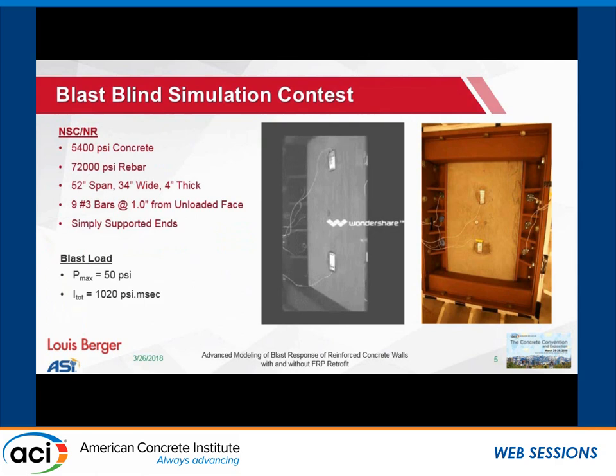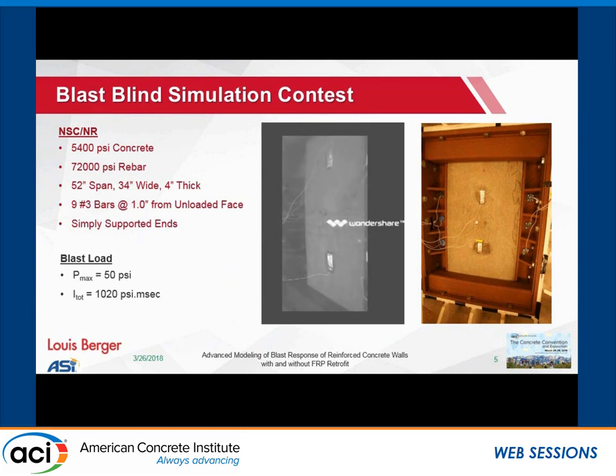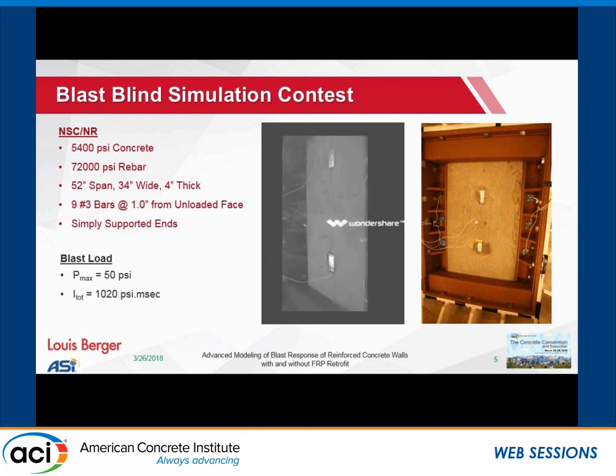This is the typical normal strength concrete case. The testing video shows the extent of damage and cracking — 5,400 PSI concrete with regular A615 steel. The blast used a shock tube at 50 PSI with a large impulse of about 1,000 PSI-milliseconds.